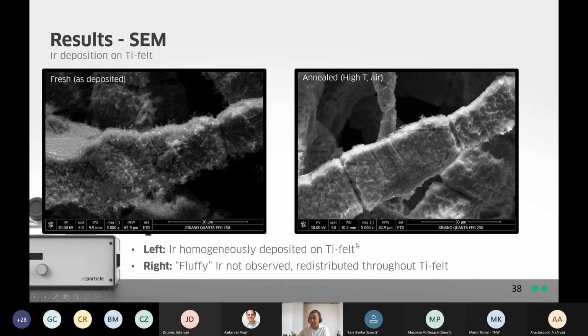We got some SEM images. So here on the left, I show you the SEM image of the as deposited material. You can see these lightly fluffy particles here that are homogeneously distributed across the titanium felt. And these are then the iridium nanoparticles that have deposited across the titanium felt. On the right, we have the SEM image of the annealed or calcined sample. And what you can see is we've completely lost the fluffy material that was deposited. And this indicates that our iridium has indeed redistributed in the oxidic phase across the entire titanium felt.